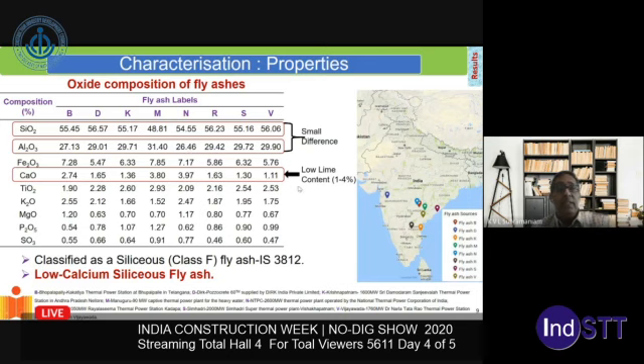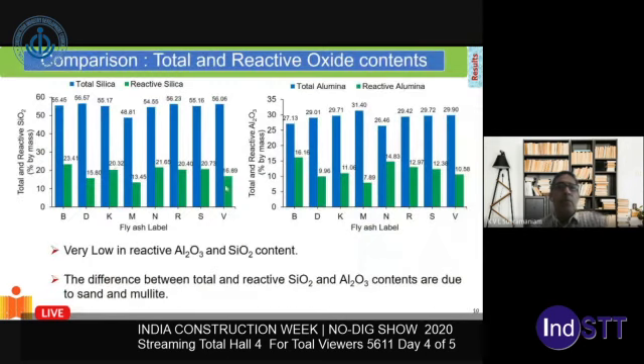The one unique thing about fly ash that's produced in India, or I should say the fly ash that is predominantly produced in India, is that most of it has very low lime content. It's very, very low. So most of it is class F fly ash. Now, what we did is we basically, from characterization, established the reactive silica and the reactive alumina in the fly ash. These are the two reactive elements in fly ash, which are most beneficial for use in cementitious systems or in alternate binders that are being produced nowadays.